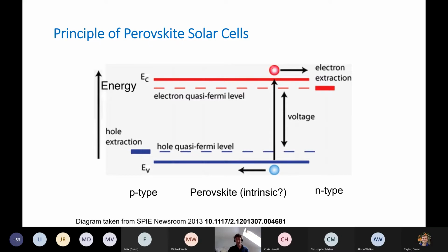But in a real system, or at least in any system, this electron can also recombine back with the hole that it left. That recombination, or relaxation of an electron from the conduction band back to the valence band, is the opposite process of light absorption, and it results in the emission of a photon. That is a recombination process in any semiconductor, and that has to happen. There's a reciprocity between absorption and emission, and any material that's a strong absorber will also be a strong emitter. So a perfect solar cell, if there are no losses in the material, has 100% efficiency of re-emission of light when you're not extracting it.